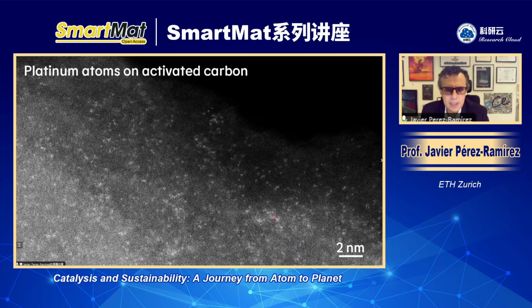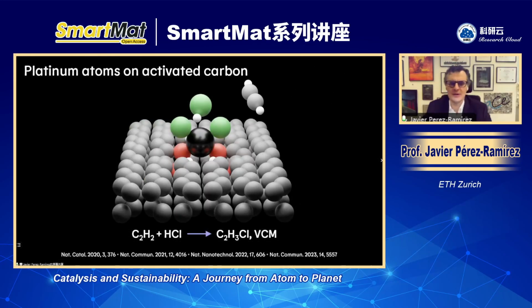And we are using these materials extensively for multiple reactions. And I want to show you one reaction which is very important, particularly in China. And this is the production of vinyl chloride via acetylene hydrochlorination. Platinum single atoms stabilized on carbon are extremely stable materials for hydrochlorinating acetylene into VCM or vinyl chloride monomer. And that's a technology that is very important to replace mercury catalysts that are used today to produce this PVC precursor. And I want to show you this because that's the reaction I'm referring to. So acetylene hydrochlorination to vinyl chloride monomer.